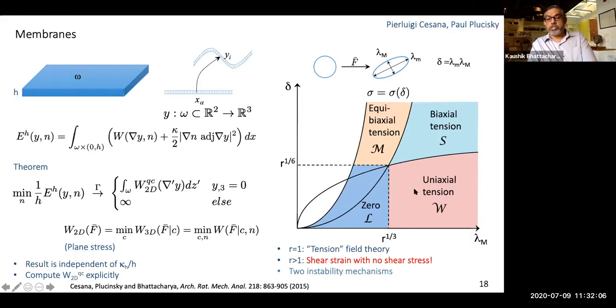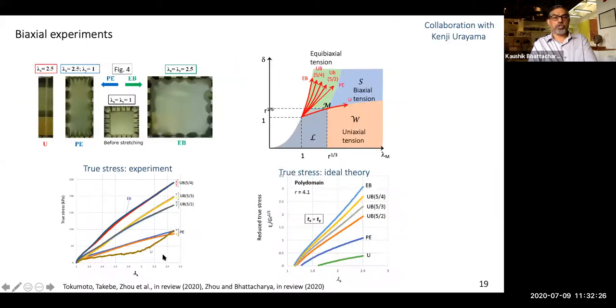This is known even in rubber-like materials, and it's often described using what is called the tension field theory, because you only have uniaxial tension. This is the new regime that this material offers. And so let's try to see whether you can probe this regime using experiments. I'm going to describe a collaboration with Kenji Urayama. They built a biaxial machine so that they can stretch in two directions. And what you try to do is to stretch in all of these directions so that you are going to this region of equibiaxial tension.